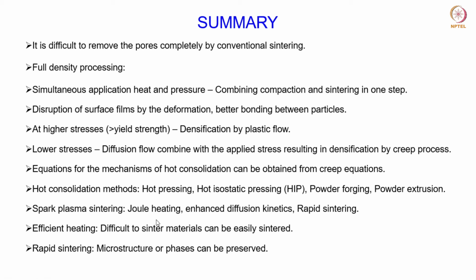Okay, so unlike the conventional sintering process or the hot pressing process, here in case of spark plasma sintering, the heating occurs internally by Joule heating. Okay, so here what is done is an electrical current is passed in the form of a DC pulse, and the heating is achieved with the heating effect of that particular current. Okay, so that is basically the Joule heating, which is the heating effect of electrical current. Okay, and this happens across the particle to particle contacts when a spark results due to the application of a very high current, and therefore the heating is quite intense and also uniform across the entire compact.